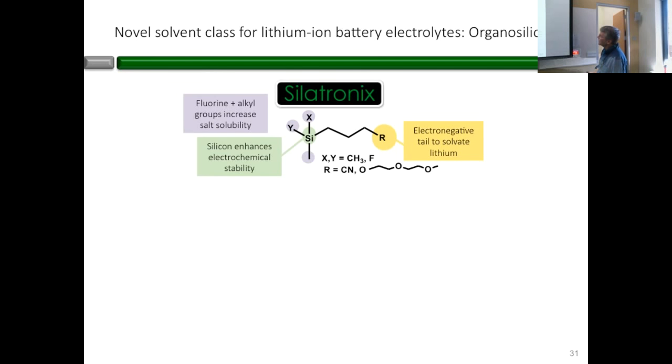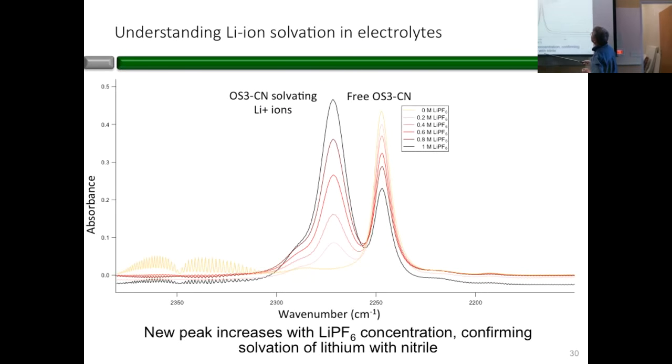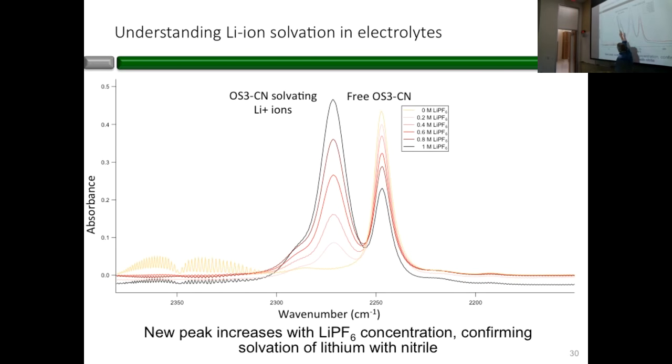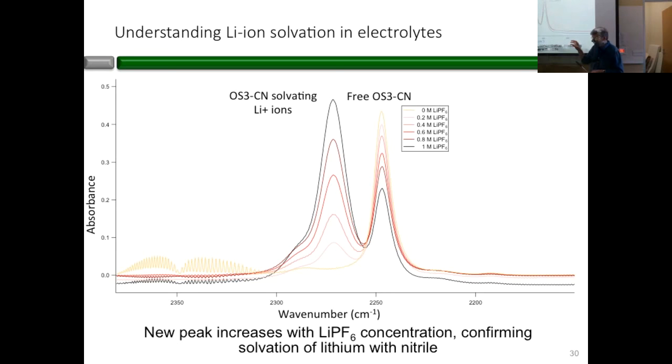So we also look a little bit at, I'm pretty much done here. One of the other things that we can do is look at, I mentioned that this lithium chelating group, either the 3 oxygens or the cyano group, solvates the lithium, right? And it turns out that solvation is also very important. I mentioned to you that in the case of the carbonate electrolyte, there's this layer called the solid electrolyte interface layer. And one role for that layer is to strip away the solvent in such a way that the lithium can go into the graphite without trying to pull solvent molecules with it.